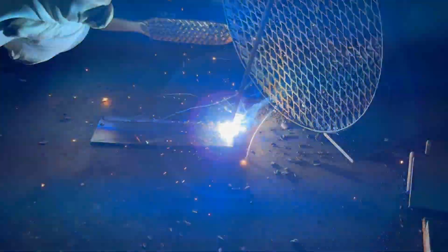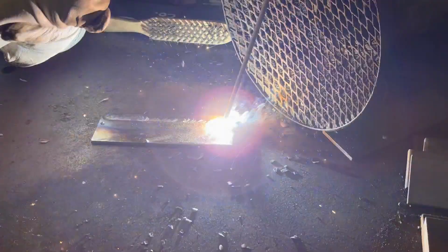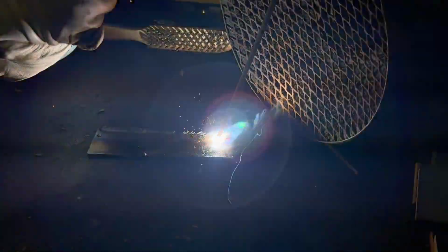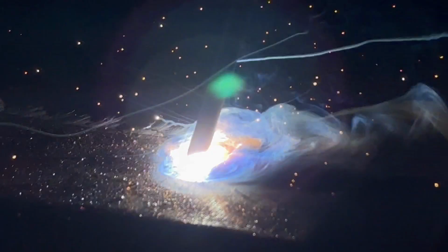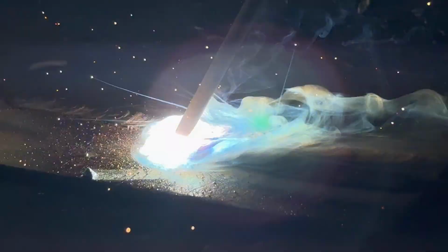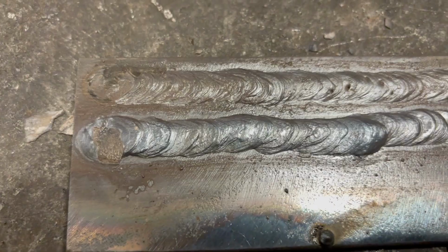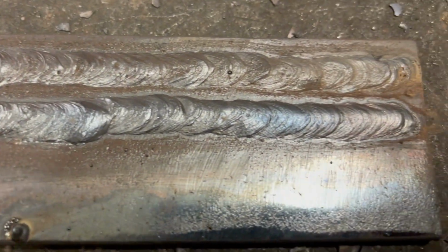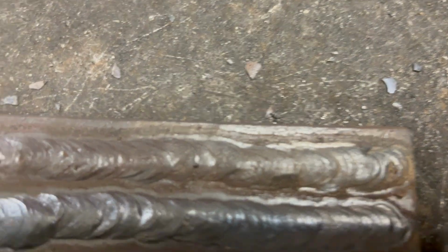For our second issue, we're looking at using the wrong rod angle and pushing the weld pool instead of pulling it. Pushing the rod prevents the flux from staying at the back of the pool, which can cause a lack of fusion and create slag traps. The weld pool also tends to run away too quickly, making it harder to control and maintain a consistent bead. With no pool control, the ripples don't form properly and the weld looks coarse and uneven, making it look like your apprentice has done it. As you can see from the finished weld, we've got no uniformity, the run's not very straight and our ripples are all over the place.